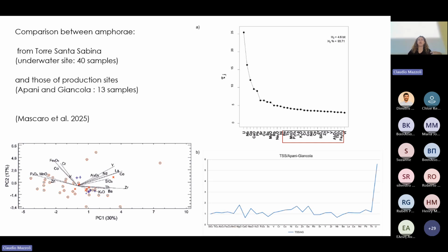So this can also be expressed in terms of the variation that we see in elements, considering the average composition of the material coming from the production site and the one from underwater. So you take your samples from underwater, the average of each chemical element, and you divide that by the average of that chemical element from the sample from the land, from the production site. You normalize your data to the reference data, right? And when you see that the element is close to 1, it means that there is not much difference between the original one and the one from underwater. So the element is stable.